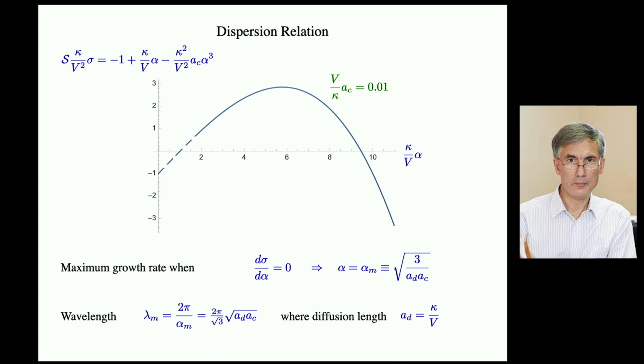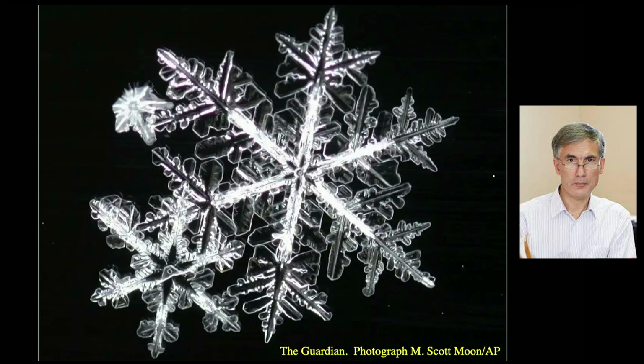Okay? And of course, it's this instability that gives rise to snowflake patterns, for example, and gives rise to the mushy layer that we had in our plastic bags at the beginning of the picture. The diffusion length for a snowflake is really the size of the envelope. That snowflake will grow basically limited by thermal diffusion of the thermal halo that's around the snowflake.